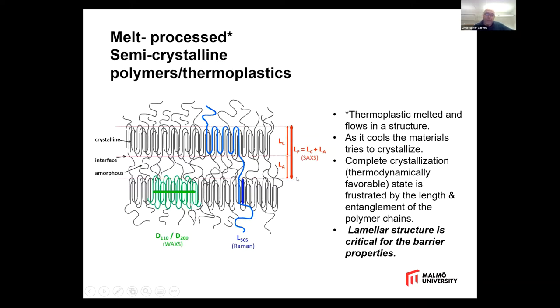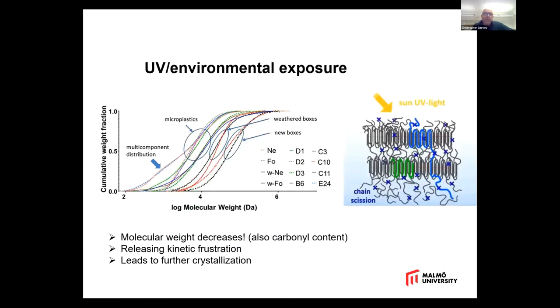And how much crystalline material versus how much amorphous material is the crystallinity, and it's related to how effectively it crystallizes. We have the perspective of small angle X-ray scattering on this, which measures what I call a linear crystallinity. So the ratio of this distance to this distance. I also use a Raman technique to measure the thickness of this independently. And also I look at how ordered it is in this direction. And what I'm looking at is what happens to the lamellar structure, which is critical for the barrier properties of this material, with ocean degradation. So the first thing that happens to these materials when you put them in the sun, and you've probably noticed this with even plastic furniture that you've got outside in the harsh Australian sun, is that it starts to become brittle.